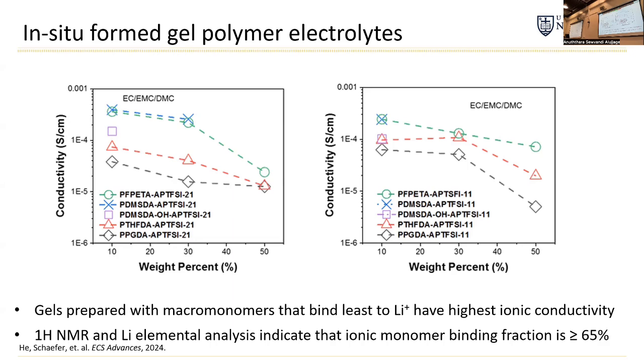And overall, we found that what we had seen before for the ex situ polymerized gels held for the in situ polymerized ones. So if we use macro monomers that have lower binding energy to lithium, they have the highest conductivity for the gel case. You can see the conductivities vary by about an order of magnitude here, and we're in the range of above 10 to the -4 at room temperature. The ones that performed best in terms of conductivity were the perfluoropolyethers and the PDMS.